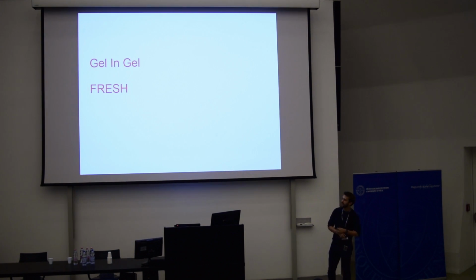The last thing I wanted to present to you is this idea of gel-in-gel printing. One of the hardest things in bioprinting, especially with the technology that we use, which is deposit-based printing, is creating overhangs. In normal plastic 3D printing, as you can see here in a lot of the booths, people use support-based structures. The support really helps maintain the overhang as you're printing it. But in bioprinting, gels don't really allow you to do that. There's no real support gel-based structure.